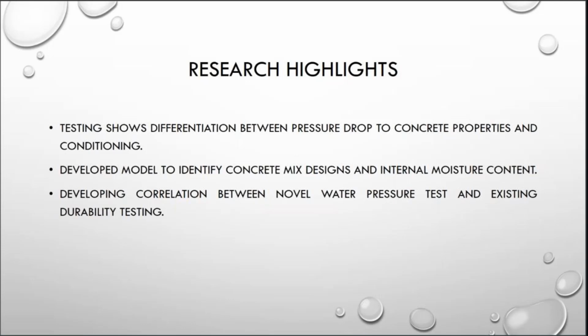And so knowing the moisture content, I think you can determine important parameters such as porosity of concrete, for example. We're stretching a little bit, but we're trying to get there. It's the pore sizes, air space, and also the distribution of the pore sizes. But in a more practical sense, if you're not going to be able to know that in situ, we feel that we can control the concrete in the field by drying the concrete or wetting the concrete and doing the same type of test we did in the laboratory, really to get different ways to gauge the concrete.